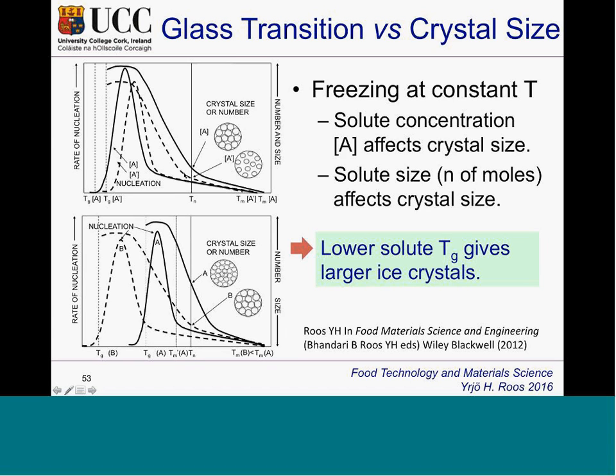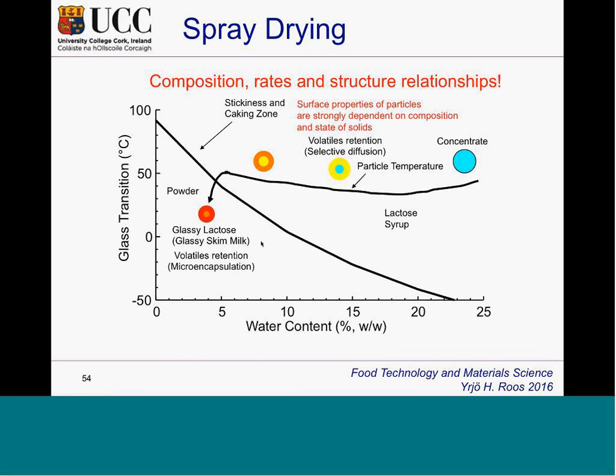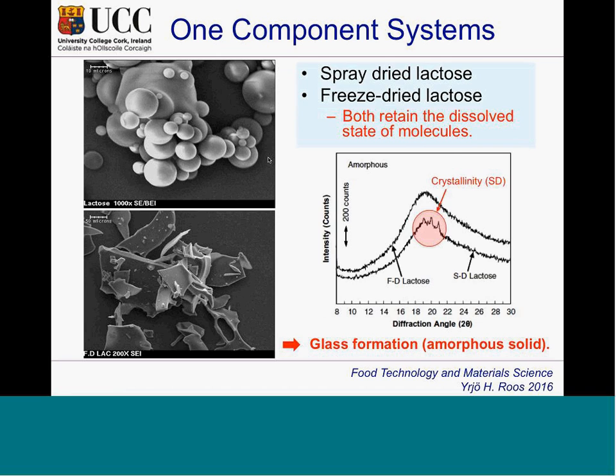Drying, there's quite a lot to understand in structural formation because of solids characterization. This is a schematic of a concentrate going to the dryer and then cooling a little bit because of evaporation, forming a crust that is then dried on the surface, and then cooling that to below the transition to allow particle flow. You have particles that flow if they are solid. If they are somewhat liquid on the surface, they go together and then form one single part. So if we look at one component systems, we have lactose freeze drying or spray drying, and we have the crystallinities varying depending on how they have been dried. In spray drying, we tend to get more crystallinity than in freeze drying.